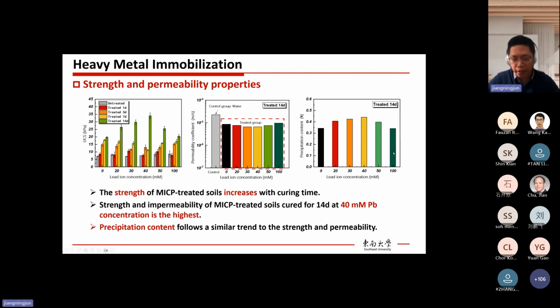Then for 50 and 100 case, although we have even more lead ions, the reaction is simply too slow. So it cannot generate a sufficient amount of precipitation compared with the 40 millimole case. So that's why we think the 40 millimole case has the highest precipitation content.